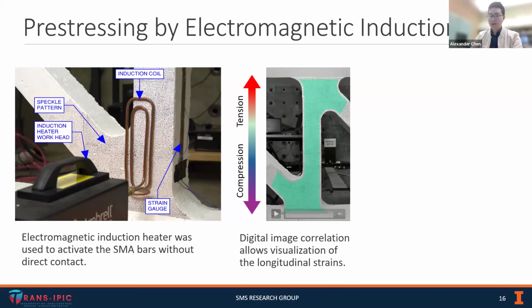And I'm going to play a video. This is a time lapse of the process. So this is the SMAs being heated up as well as cooling back down to ambient temperature. And you can see that this blue region in the middle is an indication that the concrete there is being compressed by the activated SMA bars.